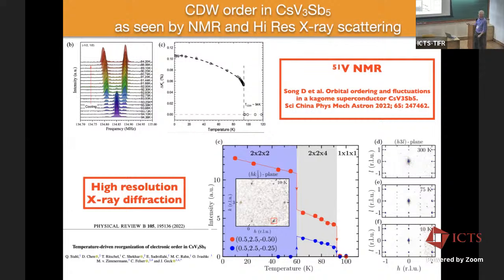Anyway, the only reason I wanted to call out this particular high-resolution X-ray scattering measurement instead of any of the other 4 or 5 that have been published is that they're similar to this, but they're not the same as this. And Stephen Wilson discussed this in his talk. He talked about the variation that you can get in the stacking periodicity that's observed in these sorts of experiments. That can be, well, I wouldn't say controlled is too strong a word, but that can be altered by quench rate and exactly how well you equilibrate the sample, among other reasons. But the reason I'm showing this is that it was performed by some of our collaborators on the same samples that we performed our measurements on, right? So that's why I'm showing it. And once again, it shows this very abrupt and very discontinuous phase transition at about 94 Kelvin, okay?